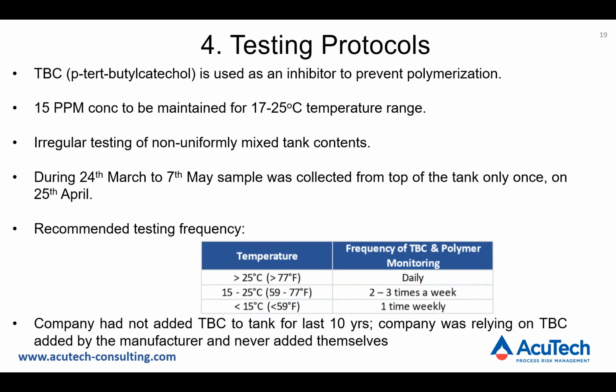However, there were no styrene deliveries or usage during the lockdown period, which allowed the TBC level in the tank to drop, again undetected and aggravated by the loss of mixing due to the aforementioned circulation piping change, which also allowed for temperature differentials inside the tank. Higher temperatures increase the depletion rate of the inhibitor.